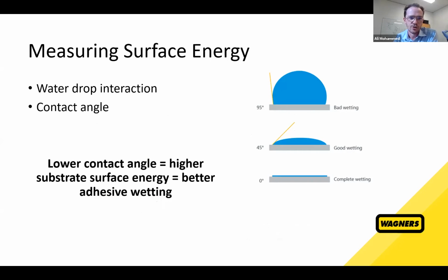Okay, so we've asked ourselves, how do we actually measure or evaluate the surface energy of a surface? Back in the day they used dyne pens and various other things like that, whereby you were given a set of pens that you used to mark a surface, and that pen would then indicate whether the surface was high or low surface energy and give you a rough approximation of what that surface energy was. But these days we've gotten a lot more advanced. The best way to do it is to have a consistent way of measuring. Your substrate's the variable. You want to know what the surface energy of your substrate is, so the way you measure it should be consistent. So you start off with a liquid, most often some sort of very clean water, and they use a water drop and how it interacts with the surface to assess the surface energy of that substrate.